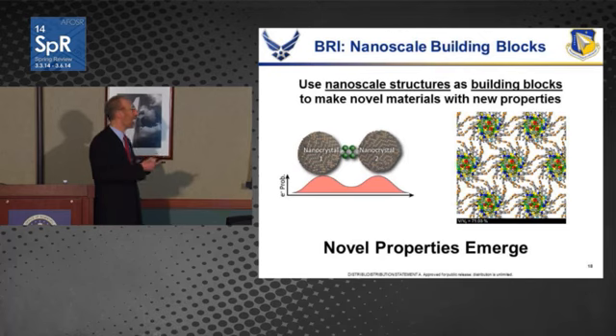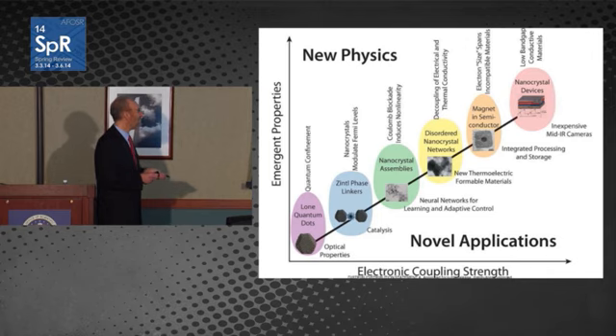And as you can see, you can control the electronic properties maybe in a different way from the mechanical properties. You can decouple the electronic and mechanical coupling between these to lead to thermoelectric materials, or ways that we can control thermal conductivity. And we've got novel ways that we can look at mechanical structures as well. So there are many applications of the electronic coupling. As we change the coupling strength, we can find many different electronic properties arise. We can control the optical properties. We can control catalysis as we get more coupling. We can get thermoelectric materials, even computationally interesting materials, or mid-infrared cameras, all as a function of these coupling strengths. So these are some of the things that we hope to explore in this type of BRI.